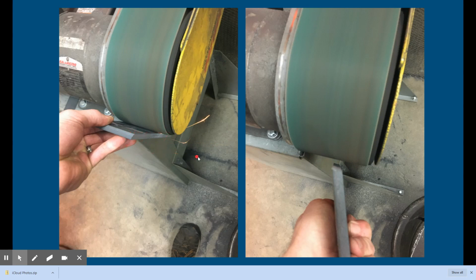You don't have to take the mill scale off, but I highly recommend it. It's going to make a much cleaner weld. It's going to help with several things. Undercut, for one, on the front on your cap. If you've got mill scale on there, you're more likely to have undercut. It's not a guarantee, but again, you want to try and do this right, and the right way to do it would be to take that mill scale off.